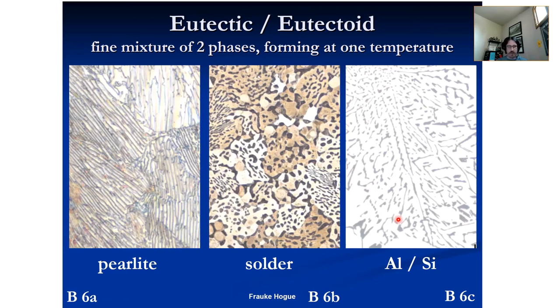In solder, there's either a tin-rich phase or a lead-rich phase; if it's tin-bismuth, there's a tin-rich phase and a bismuth-rich phase. Looking at other techniques: metallography gives us information, and you can actually see chemically defined phases via the SEM. This is eutectic solder — tin-bismuth. The crystallographic phases can be somewhat observed. This is done with a backscatter electron detector, which allows you to get similar information to optical metallography, with the advantage that you don't have to prep specimens to a mirror finish for phase characterization.